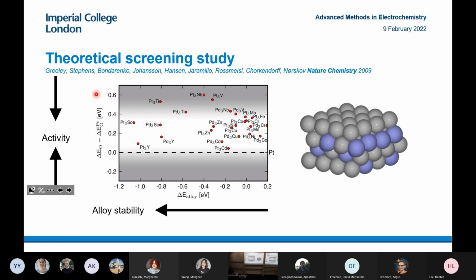On the y-axis, they've got a descriptor for activity, which is oxygen binding. So they think this is pure platinum. They think the ideal activity should be around here. And the descriptor for stability, as I mentioned, was the alloying energy. So what you can see is that many of the well-known alloys like platinum nickel and platinum cobalt have alloying energy which is not particularly negative, which means they're not very stable. But alloys like platinum yttrium and platinum scandium have very negative alloying energy.